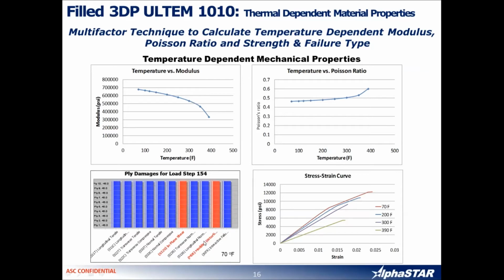On the bottom left, you see a progressive failure analysis being performed for a given layup, a plus minus 45 degree layup, for 70 degree Fahrenheit temperature material properties. The mode of failure shown here through the thickness is in-plane shear and MDE, which is modified distortion energy, which in-plane shear triggers basically.